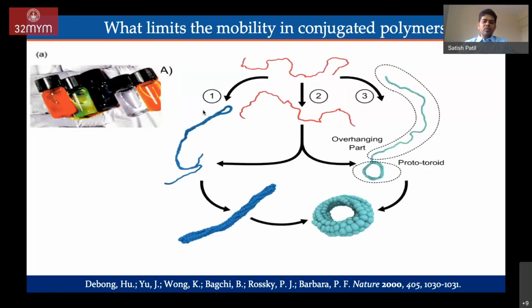For example, it depends upon the nature of the backbone. A polymer can adopt a coil, it can also form toroids, and it can also form a bundle of fibers. That depends upon several thermodynamic parameters. For example, entropy and enthalpy control the kind of conformation these polymers adopt. The chain flexibility essentially correlates with the entropy aspects, as well as the intra-chain and interchain interactions, which relate to the enthalpy. So these are wonderful molecular solids, and it's extremely difficult to correlate the electrical properties with the structures of these polymers.